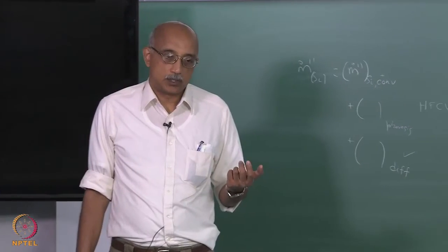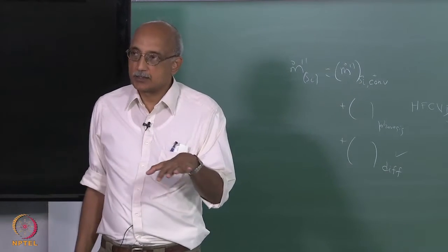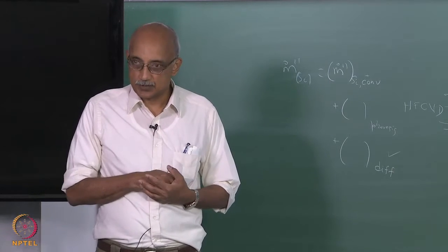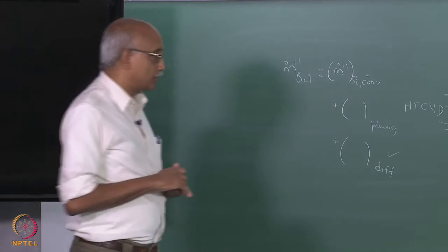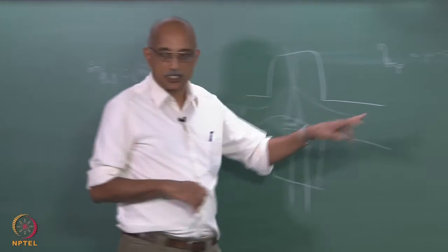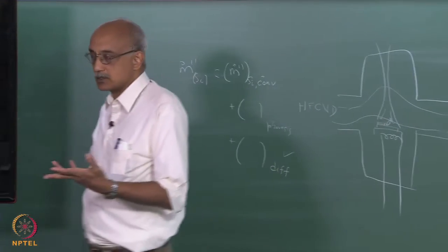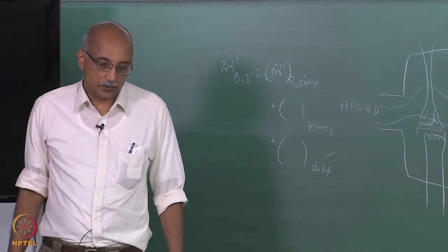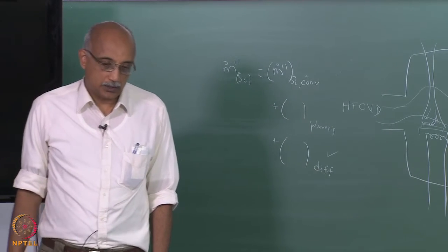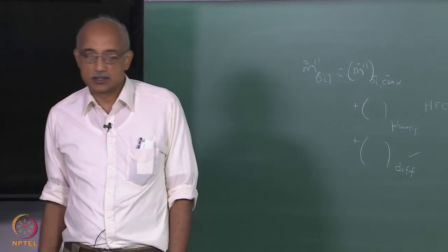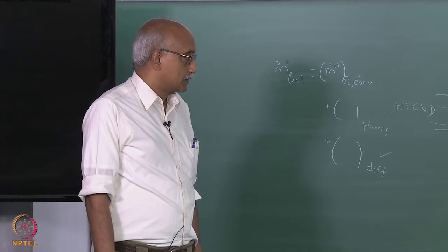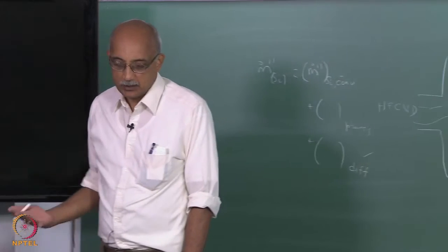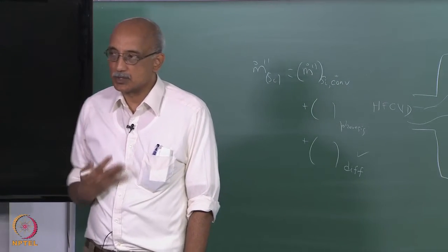Basically, the thermal diffusion will be an additional factor that drives the diffusing species from the hot filament towards the substrate. But on the other hand, it can also drive diffusion towards the walls of the chamber. So, there could be more losses due to unintended deposition around the chamber walls. But in general, as long as you are using a diffusing species that is lighter than the carrier gas, you are okay. Other types of photolytic phenomena that are present are typically negligible compared to the thermal diffusion process that is going on.